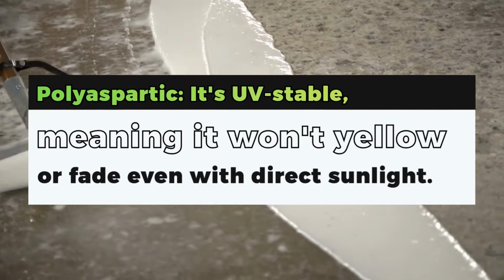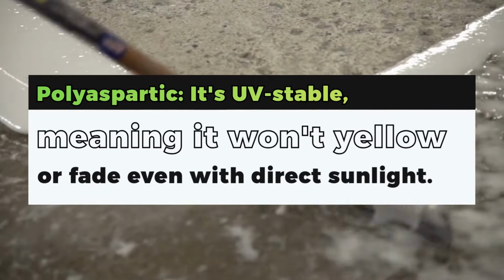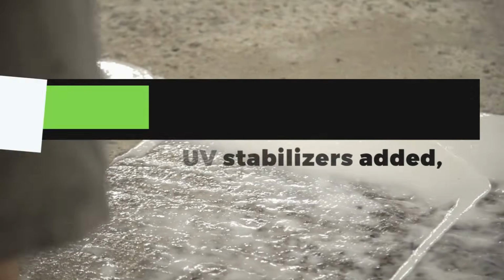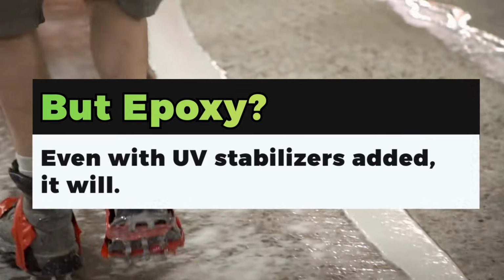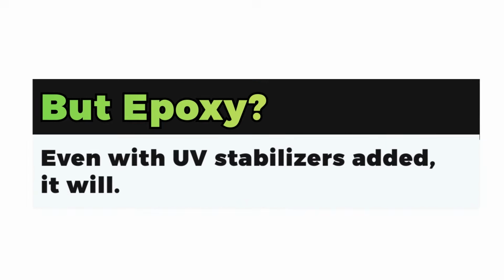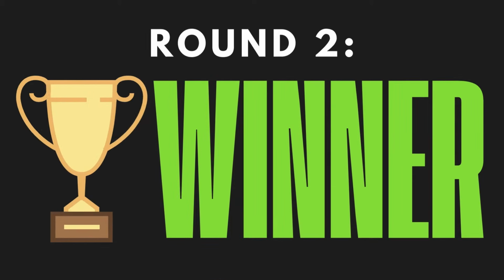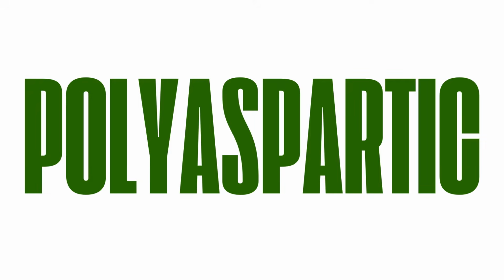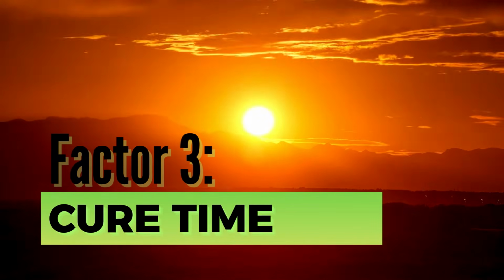Factor 2, UV resistance. Polyaspartic dominates here. It's UV stable, which means that it won't yellow or fade with direct sunlight. But epoxy, even with UV stabilizers added, will eventually amber and chalk over with time with UV exposure. In southern Utah, where High Tech Coatings is based, with over 300 days of sunshine, that can be a real problem to have with pure epoxy systems. The winner here, polyaspartic.